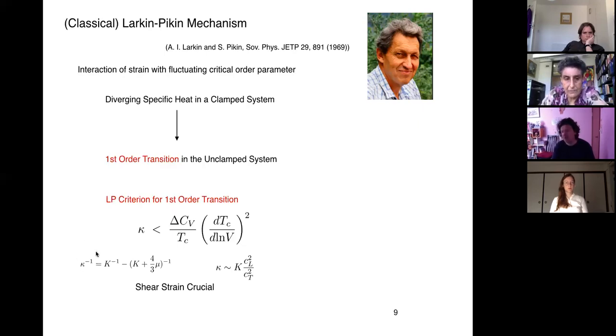And here, let's just go through these terms. Kappa is the effective bulk modulus. Big K is the bare bulk modulus, and mu is the shear modulus. And here I want to emphasize that shear is crucial. If shear is 0, like in a liquid, then we'll never satisfy this criterion. And this kappa, you might ask, what is it physically? It's essentially the bare modulus times the ratio of the longitudinal over the transverse sound velocities squared. Okay? But shear strain is crucial. They emphasized that this is only in a solid. It's not in a liquid.